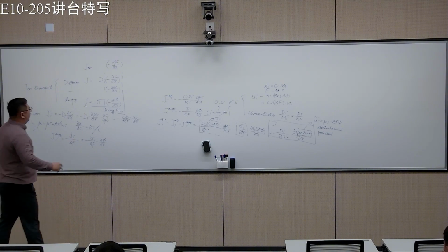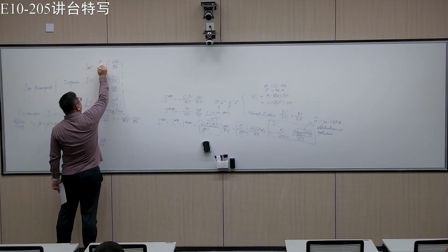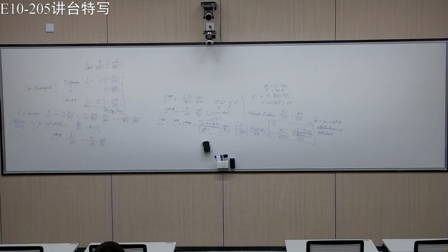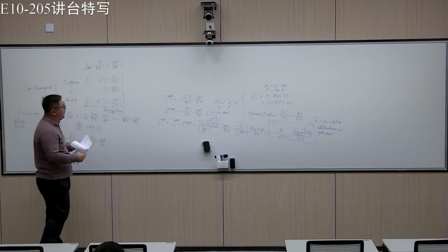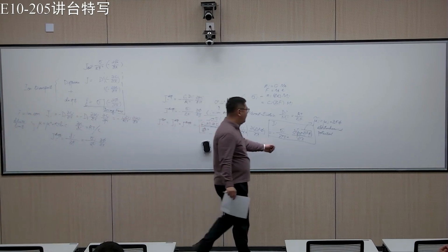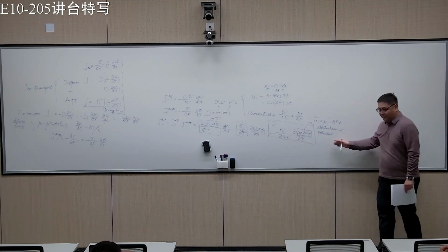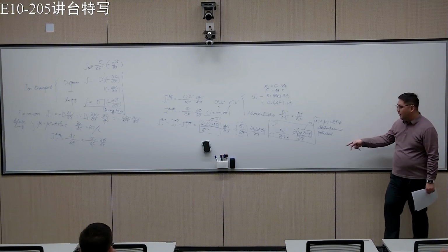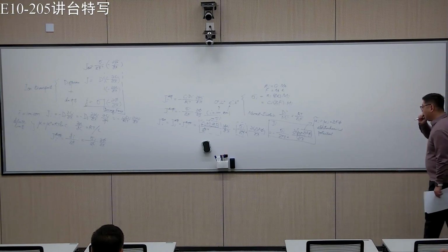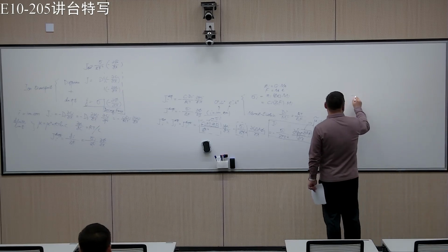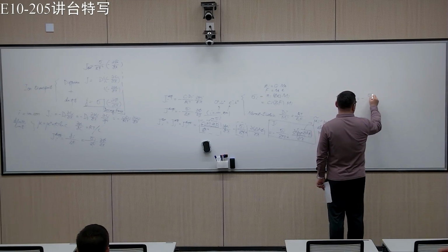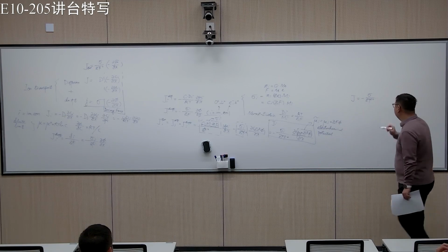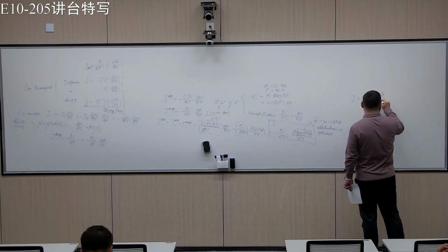What is in front of this is basically some kind of conductivity. Of course, there is a constant here. So this is a very important equation that really governs. This is true always, right? No matter whether you have only drift or only diffusion, you have this equation. Of course, if you look at this, J is sigma over Zi squared F squared times partial mu tilde partial x.